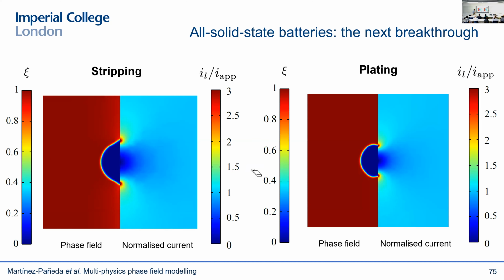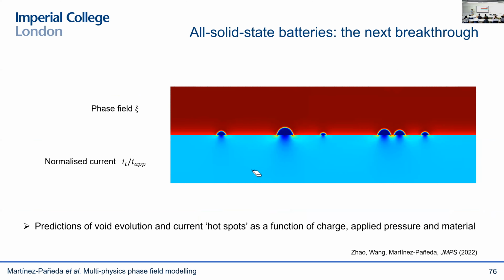And this is plating, so it's the opposite effect. Again, we are depositing lithium, so we're seeing how those voids close, and they even become occluded from the interface, as we saw in those experiments. And of course, we are not limited to modeling one void, but we can model more realistic conditions, multiple charge and discharge cycles with multiple voids. Again, trying different pressures, different cell geometries, and different interface solutions to try to understand and come up with a new solid-state battery paradigm, I would say. So again, using these multiphysics and interfacial tools to predict the behavior and map safe operation.